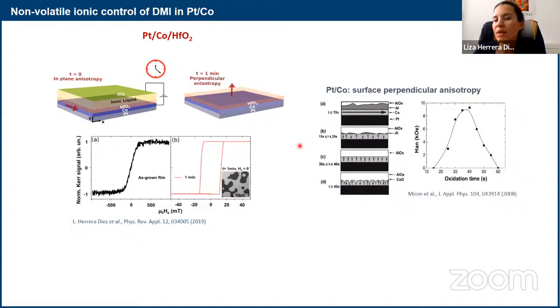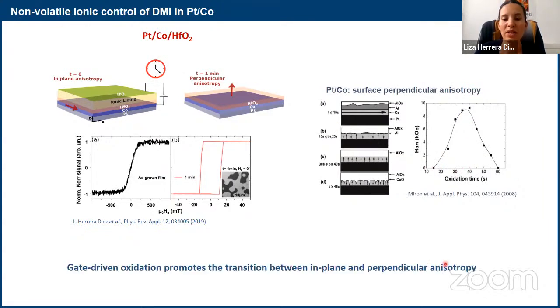And this is really something we related to immediately, because we said, well, we have an as-grown film that if we apply a negative voltage on the top electrode, that means that anything that is negatively charged will be pushed into the magnetic film. And it's highly likely that that is some oxygen species, oxygen or OH, for example. And then that would end up oxidizing the cobalt. And then we see that we go from this under-oxidized to this optimally oxidized state. And then we get PMA. So we do see very well how the gate is driving the oxidation and promoting the system to PMA.